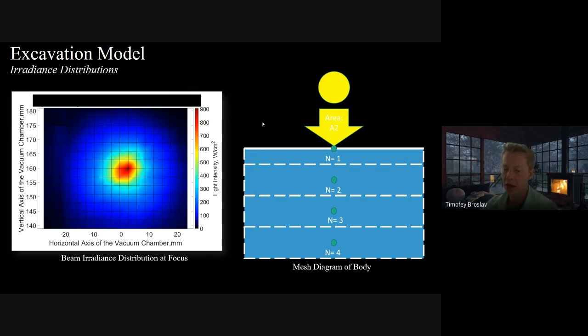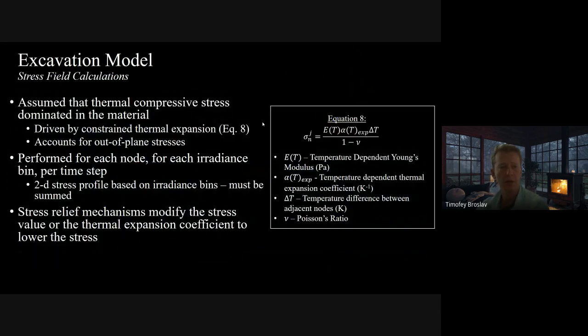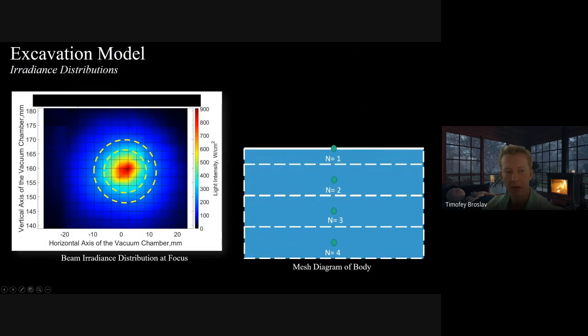And so you would have had to combine all of these thermal stress calculations that would result from this multidimensional temperature calculation and the Weibull statistical calculation. And I will go into that in a little bit. So once the thermal field was solved, the thermal compressive stresses were also solved, and it was assumed that these dominated. And so the out-of-plane equation, shown in equation 8, was used to solve for them. Like I said, it was performed for each node at each irradiance bin. In this case, this is like a bin.